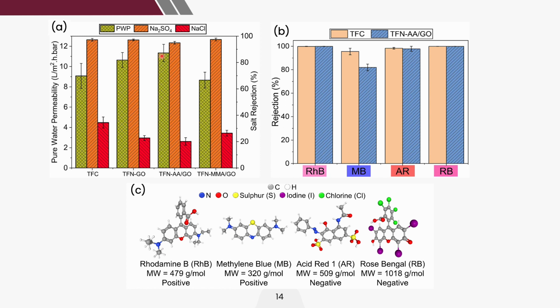further enhanced. However, if a hydrophobic monomer is used for the graphene oxide membrane modification, the flux is going down. So you will see here that the best membrane performance actually is the TFN AAGO membrane. So this membrane, although it has a lower NaCl rejection, this will not affect its performance, because if you still